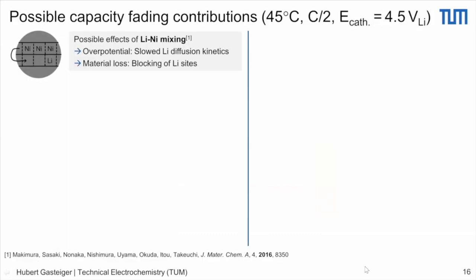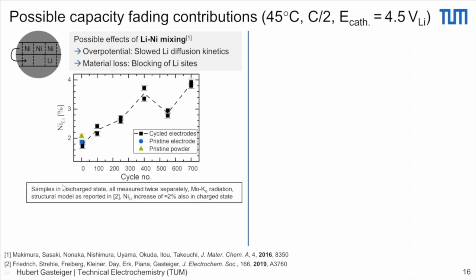So the other thing, of course, we looked at was other possible capacity fading contributions. One effect, of course, comes from lithium-nickel mixing, which we already discussed, would induce higher overpotentials. And from a Rietveld analysis, which was conducted analogously to what we had done in a previous study, we looked at the amount of nickel in the lithium layer. And what we see over these 700 cycles, we get an increase of about 2%. To be honest, we expected much more significant changes. We considered this rather small.